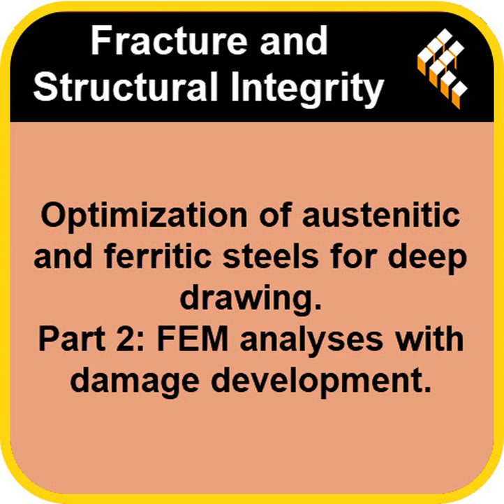When friction is high, the metal flow from under the blank holder is severely restricted. It basically gets pinned down. The strain map shows this distinctive double bell shape. Double bell. Meaning you get two zones of high strain concentration, one near where the punch starts bending the metal, and another out near the edge by the die radius. But the peak stress isn't at the very center. So where does it actually break? The failure, where the von Mises stresses spiked over 1,000 MPa, happened in the intermediate zone. That's the unsupported area of the cup wall, between the punch head and the die radius.